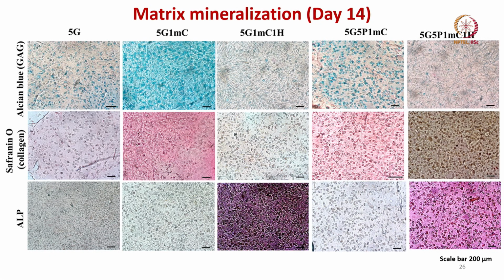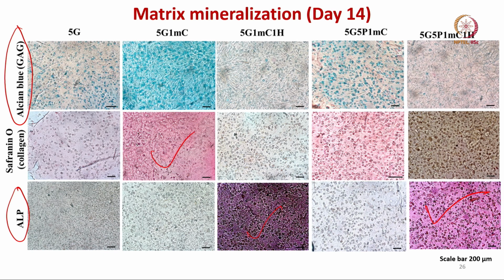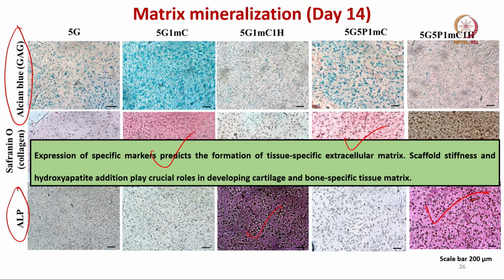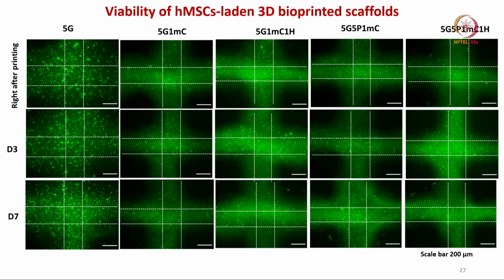In terms of matrix mineralization, in 2 weeks in culture, we did alkaline phosphatase and also Alcian blue for the GAG. You do notice that for specific compositions the ALP expression is much higher, particularly when you add hydroxyapatite into the scaffold. Whereas for other compositions without hydroxyapatite, the GAG expression and collagen expression is particularly better. So, expression specific might predict the formation of tissue specific extracellular matrix. Scaffold stiffness and hydroxyapatite play critical roles in developing cartilage and bone specific matrix.